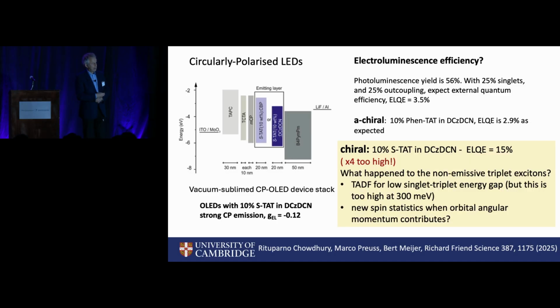But when we used the chiral material, we got the factor of 4 from the singlet versus triplets back. We're up at 15%. If we had 100% PLQE, we'd have had 30% external yield. But that is a high number, and we don't know why it works.